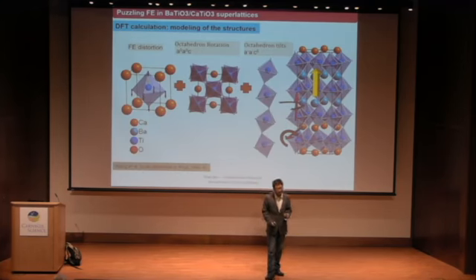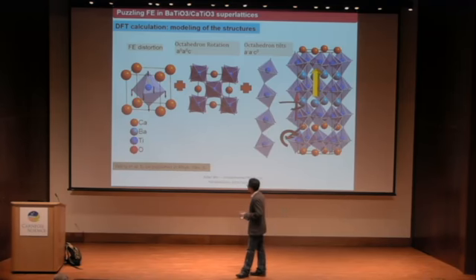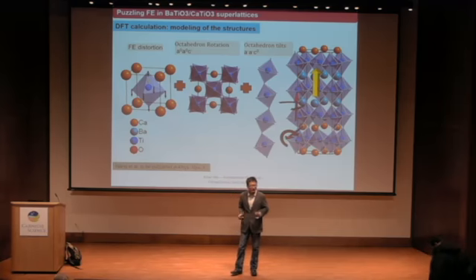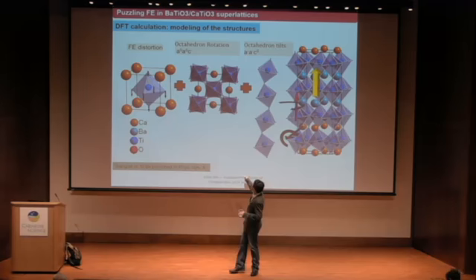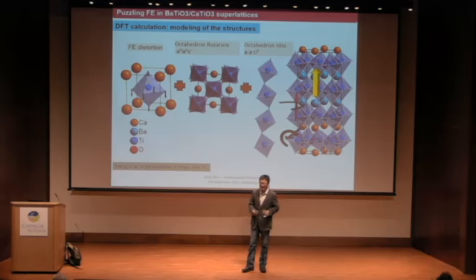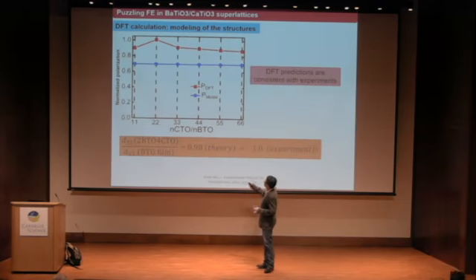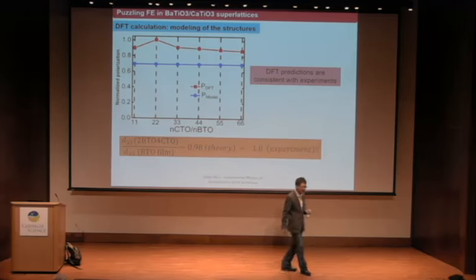It takes us a while to understand and complete the structure inside. If you are patient enough, if you model all the distortions inside, step by step - for example the ferroelectric distortions, octahedral rotations, and octahedral tiltings inside - and let the density functional minimize the total energy, then you will get a large polarization at a short period, and you will get a very similar piezoelectric constant comparable to the experiments, scaled by the BTO films.